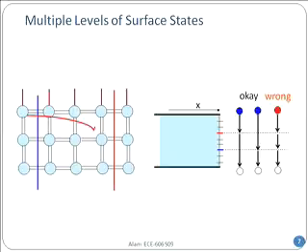These two states are far apart. They are not from the same place. Do you see that? And therefore, an electron cannot start going down to the valence band, and then all of a sudden jump 20 atoms farther to go to another level and then go down. That's not possible.